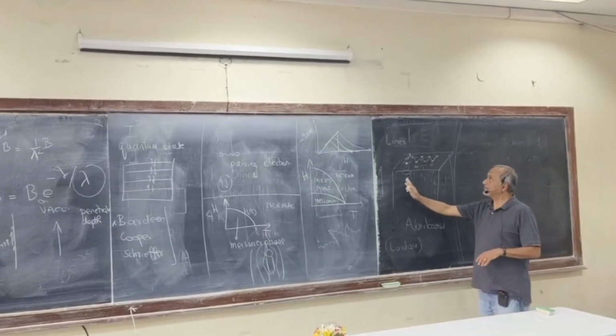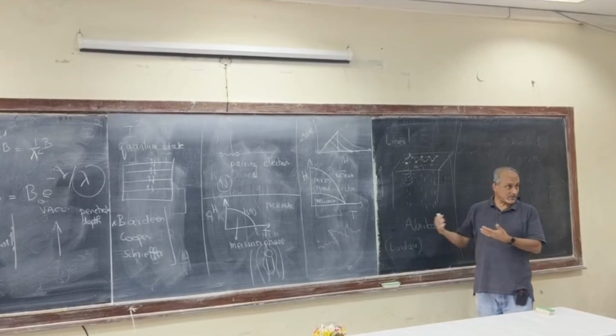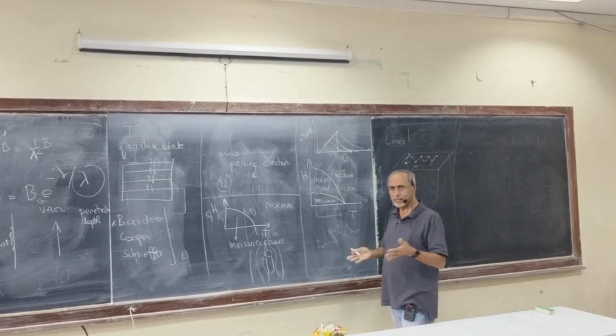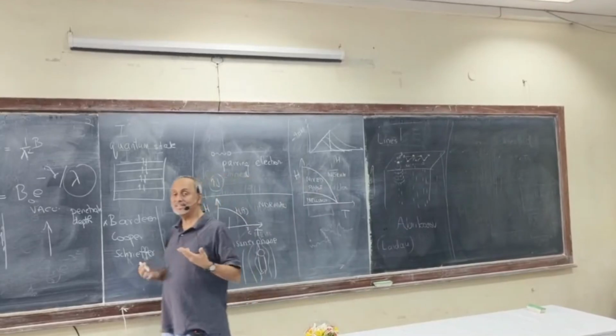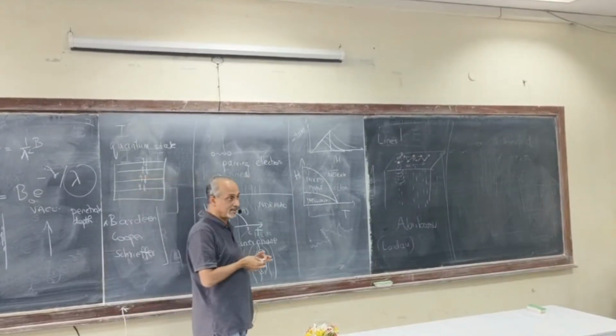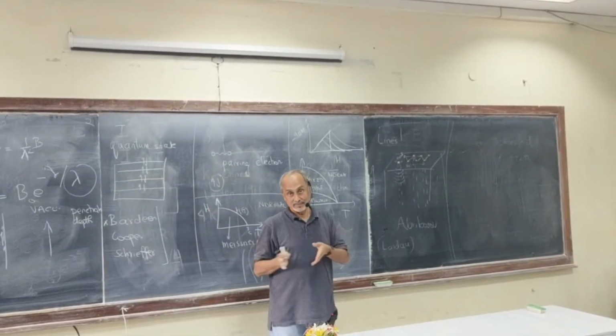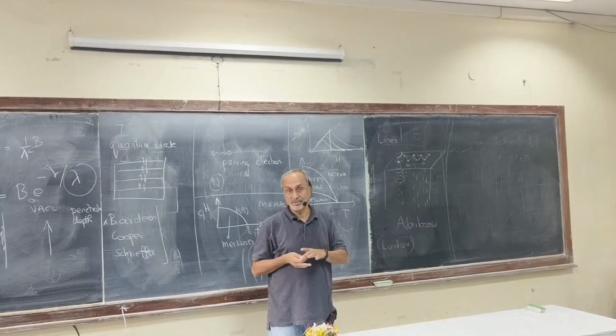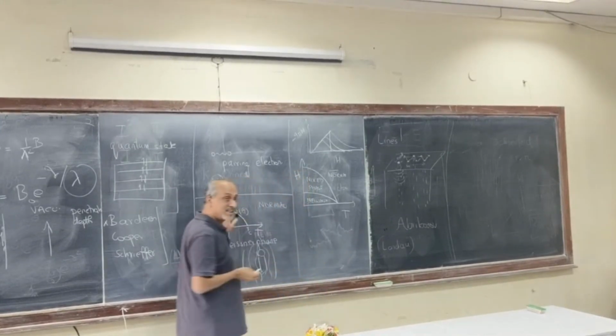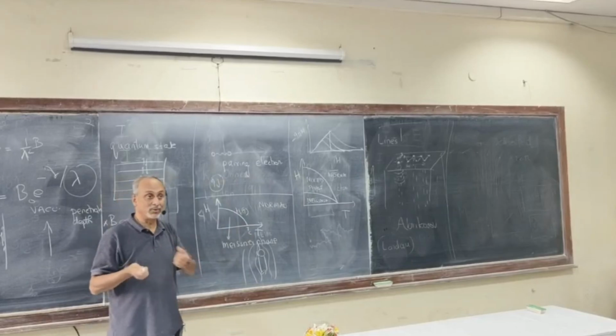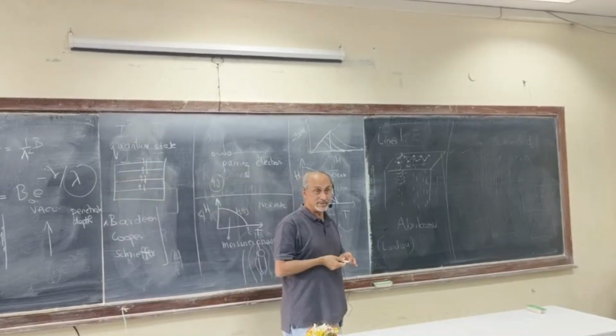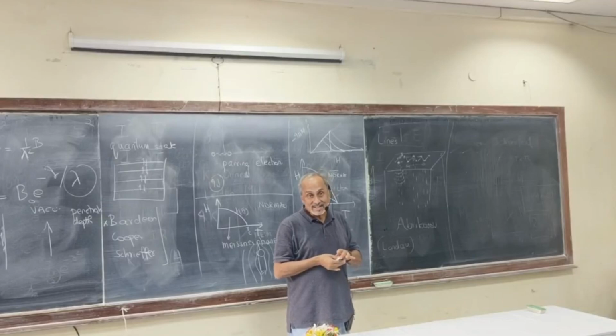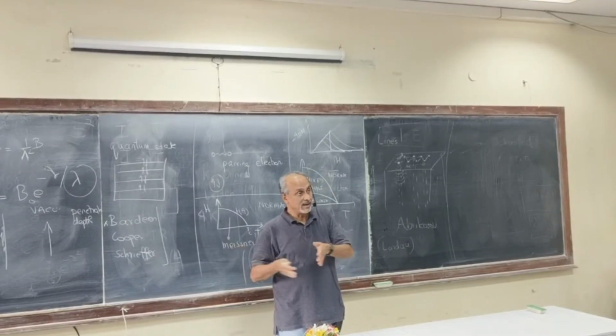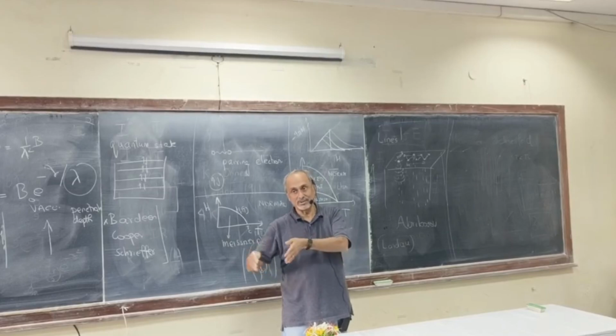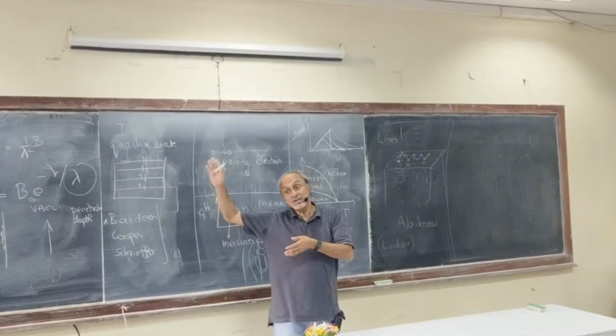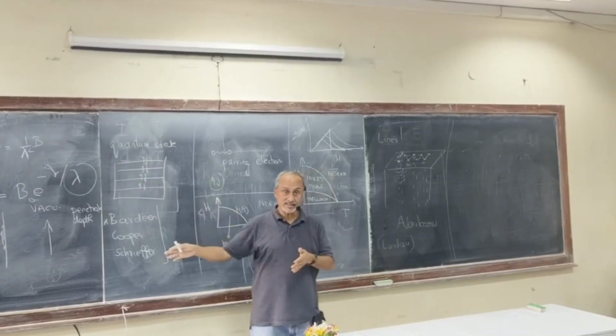All of this became very much more interesting after Abrikosov discovered this. There was some amount of work following up on that. But everything changed in 1986. In 1986, there was a revolution that happened, and that is the revolution of high temperature superconductivity. Kamerlingh Onnes was struggling to get this at 4.2 degrees Kelvin, the temperature that we utilized in here. But suddenly it seemed possible for things to become superconducting, not at 4, not at 14, not at 24, 34, 54, 64, but at something like 80 or 90 Kelvin, much larger.